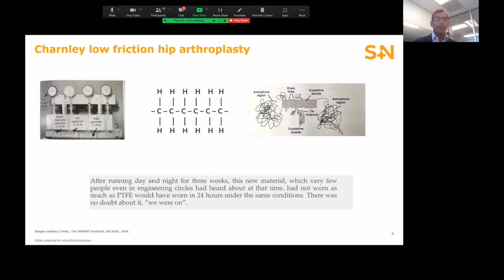So for those that may not be familiar, polyethylene is a semi-crystalline material consisting of long carbon chains with hydrogen bonded to each carbon atom. UHMWPE, or ultra-high molecular weight polyethylene, is distinct for the length of the chains, and its molecular weight is in the 3 to 6 million grams per mole range. And it's this high molecular weight that gives it improved mechanical properties over your everyday polyethylenes.